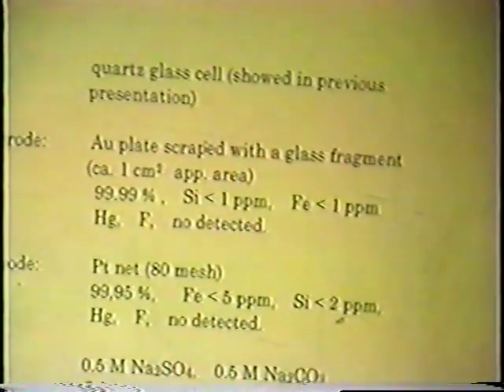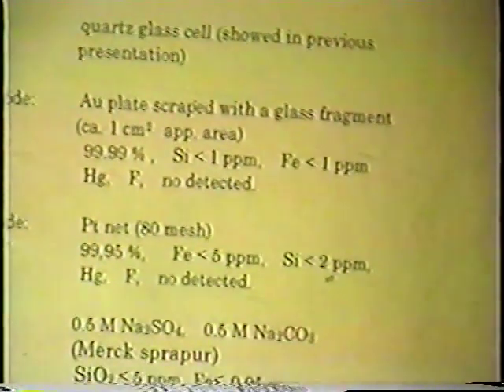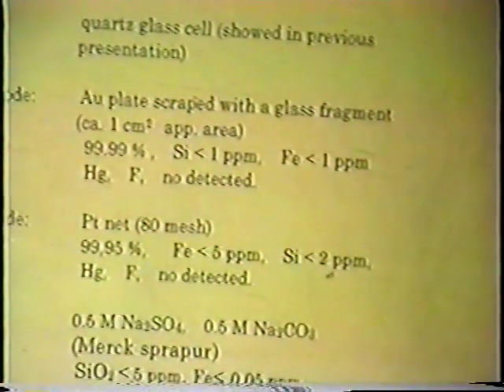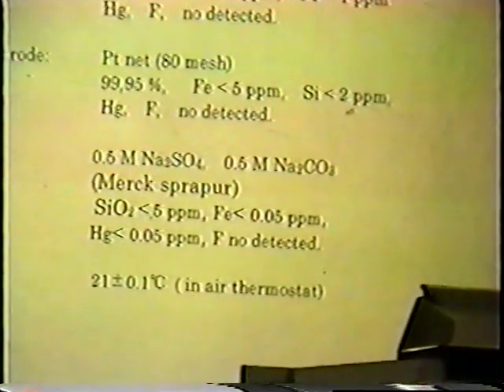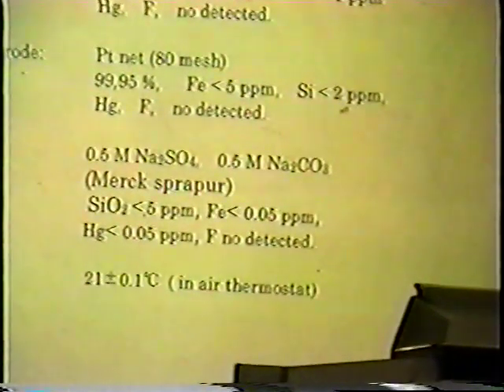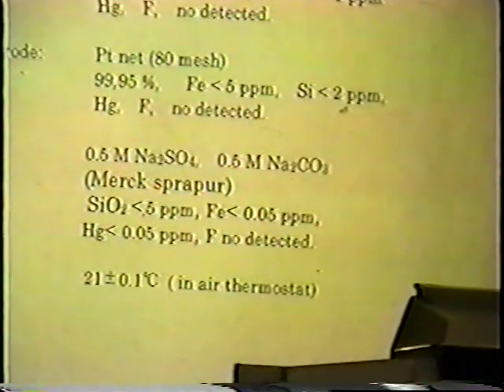The purity of solution used is as follows. Most impurity is silicon oxide, 5 ppm. Next, iron 0.05 ppm, and mercury 0.05 ppm, and other elements not detected. So this concentration is very low. So I don't consider the result obtained is influenced by such impurity.